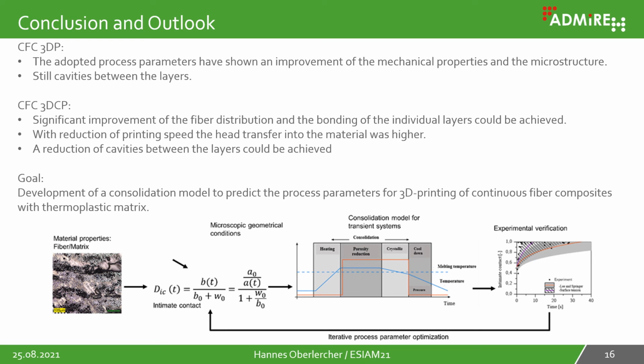For the next step, we would make bending tests and determine the bending properties of the 3D consolidation printed material. In future, the goal is to develop our own consolidation model. Initial calculations based on different consolidation models must be performed. With the first test results, we will carry out tests and compare the results with the theoretical values of this model. Several iterations will be necessary to optimize the microstructure and the mechanical properties of the material. In these iteration loops, the consolidation model will be revised, and the individual parameters like pressure, temperature and speed will be optimized with this strategy.